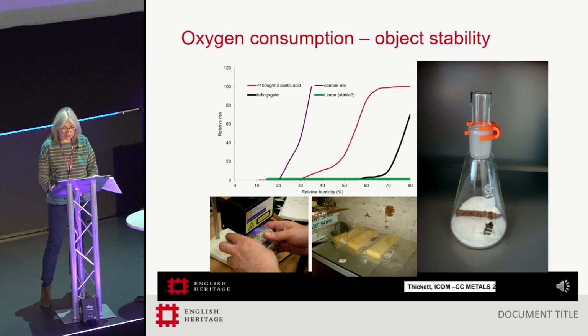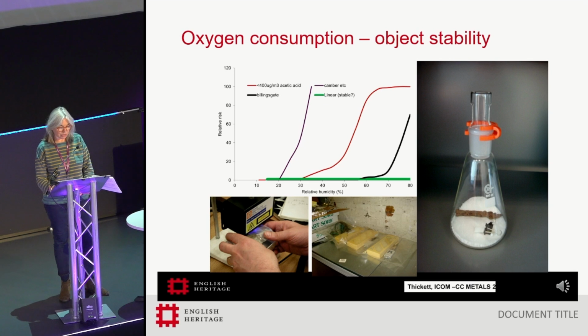For the English Heritage Iron Collection, we found 40% tested was unstable and follows the response shown previously. Approximately 60% doesn't respond at high relative humidities. Oxygen testing is picking out those objects that are stable and we don't need to do anything for. We take an oxygen reading at the start of the measurement and then another one 2 weeks later. If corrosion is happening, oxygen is used up, and so the oxygen level will be lower. This would tell us the object is not suitable for display in ambient RHs.